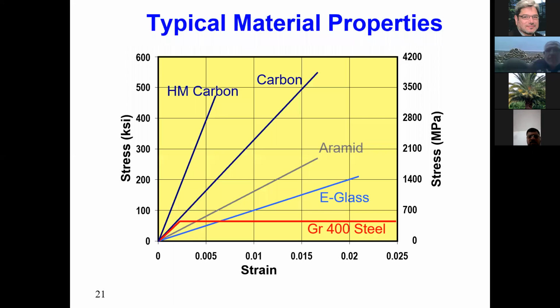This is a very typical stress strain diagram, which gives you a comparison. This vertical axis is in KSI in imperial units, and here it's translated into SI units. And this is the stress strain diagram. Typically, this is the red, this is steel. This is grade 400 steel, 400 MPa steel. It has got a yield point here at around 400 MPa.